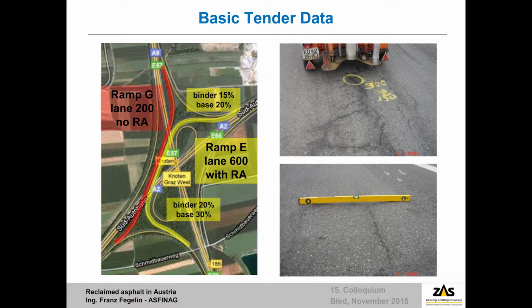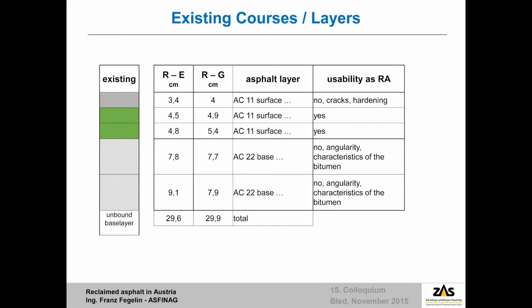In preparing the tender documents, preliminary research had to be carried out in order to know more about the required quality, because in this case we wanted to reuse the material from the same site. The evaluation of the tested sample courses showed which layers were usable and which not. The usability mainly depended on the quality of both the bitumen and stone, and especially on the percentage of round grain, which is very specific in the area in Styria and is not allowed in the Austrian standards.